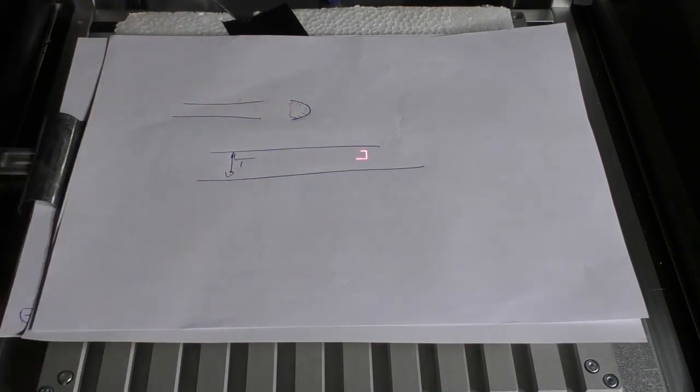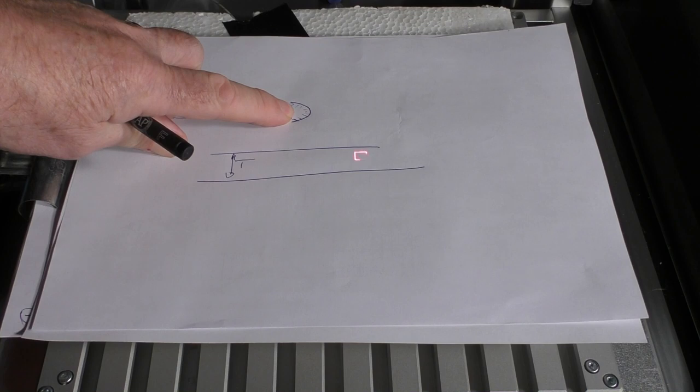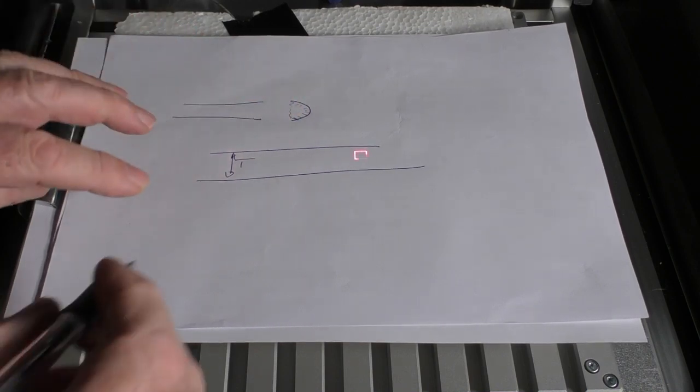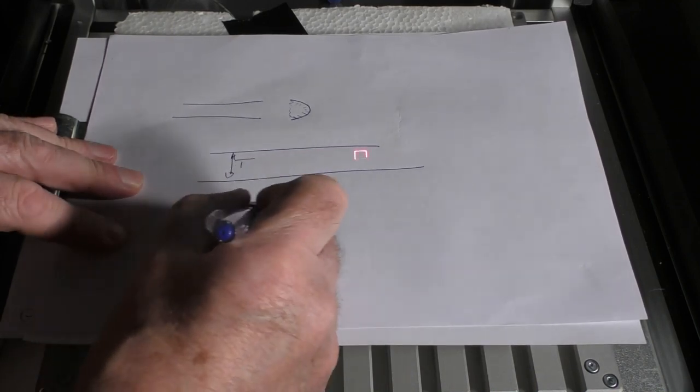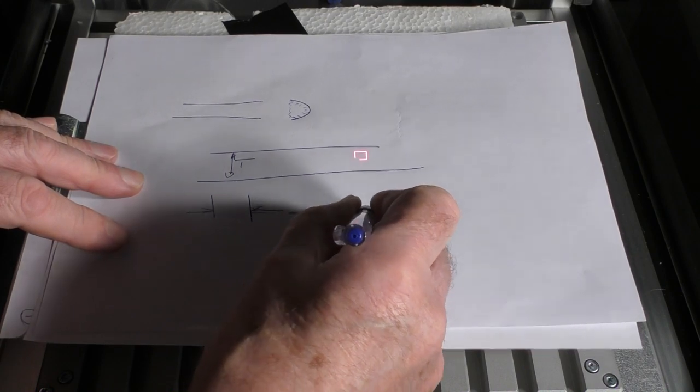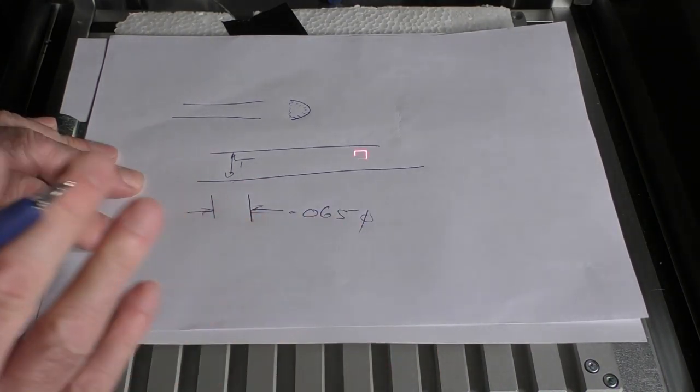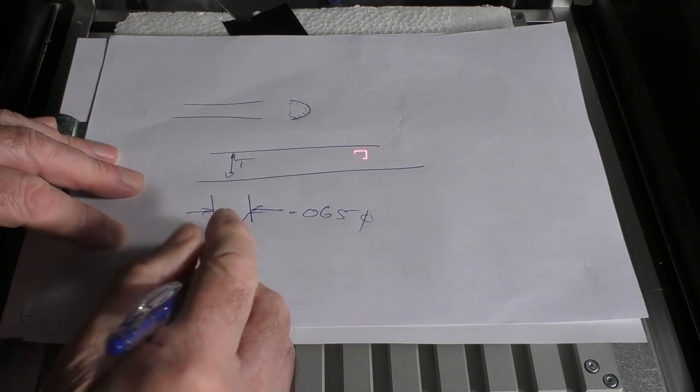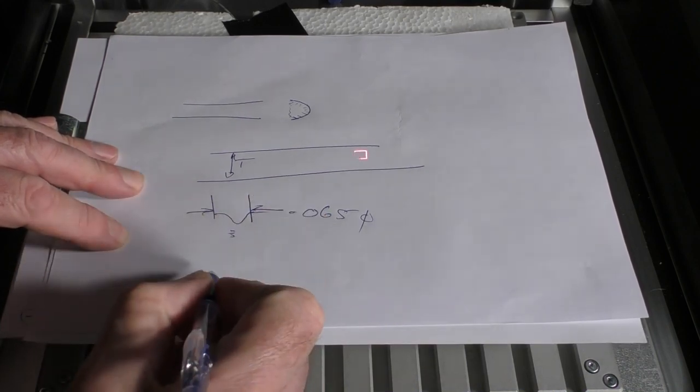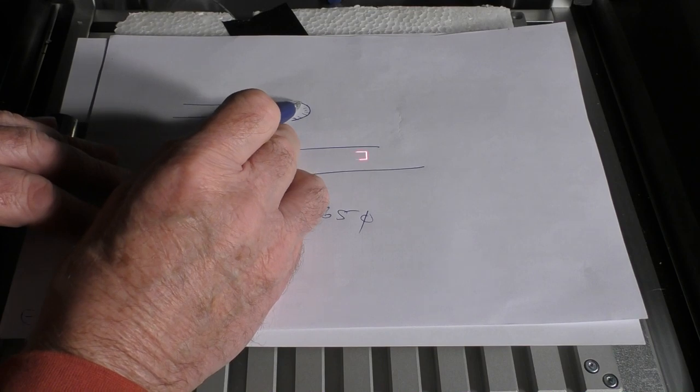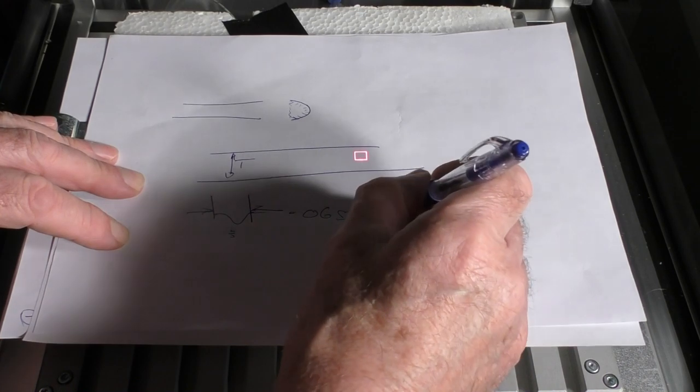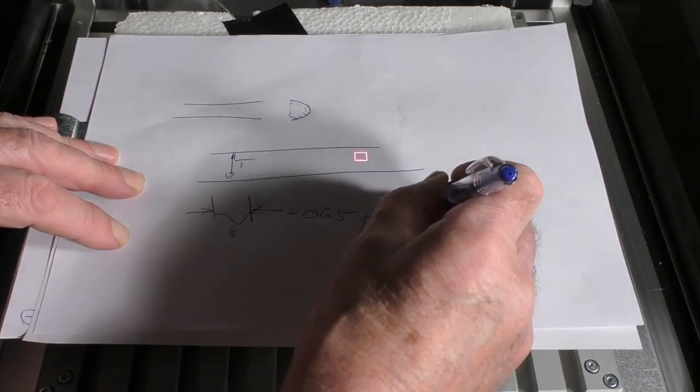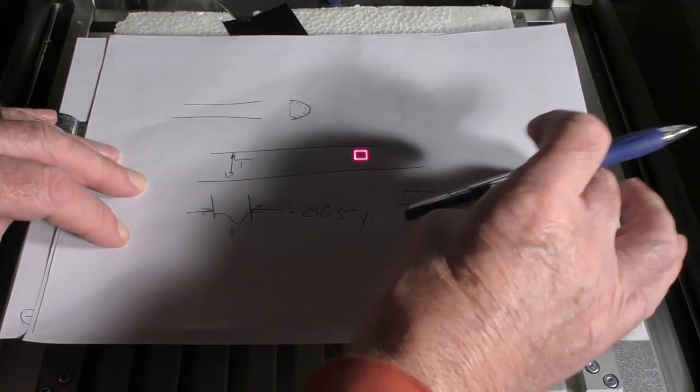This opens up many possibilities. First of all, if we're doing deep grooves like this, we're into one sort of heating situation. That is very possible because remember the beam that we're firing at the work, although it is only somewhere in the region of about 0.065 millimeters diameter, it is not 0.065 of uniform energy. The energy distribution in that beam is Gaussian. In other words, we've got a high power right in the center of the beam and it drops away to nothing towards the outside. So that would account for why we've got a bit of a groove when we do our burn and why we see these patterns of speckles which tend to be along the edge rather than the center, and we tend to get a bit of a black mark along the center of our line.